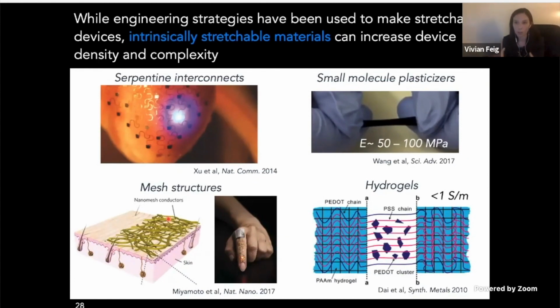And so the question that we asked ourselves was, how can we leverage these known hydrogels that are soft and stretchable and combine it with what we know about making soft conductors in order to make hydrogels that are simultaneously soft, stretchable, and conductive? To solve this problem, we wanted to see if we could make interpenetrating network hydrogels, where one network is the soft and conductive PEDOT:PSS gel that we described in the first part of this talk, and the other one is